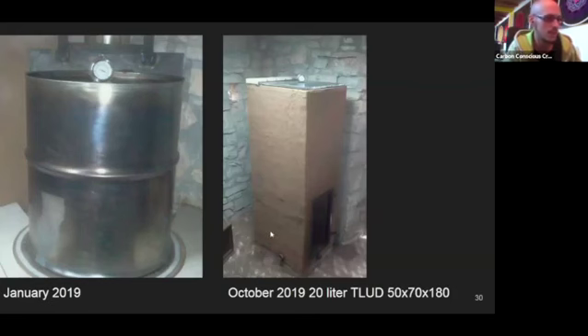Then after that, I made a large masonry system, which was still using the 20-liter TLUD. And this one was, I would say, working perfectly, because it had both a lot of direct radiant heat from the steel top, and the brick skin was light enough to start radiating heat after about an hour or so, but still had enough thermal mass to retain the heat after the stove was already out. So this would stay warm almost until the morning if I was lighting it at night a couple of times. But that was super convenient.